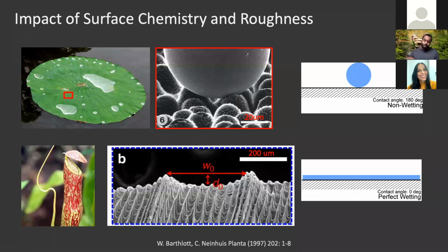And again, the opposite is true if you make a super hydrophilic surface, a surface that really, really likes water, like in the pitcher plant case. If you have this nanostructure and microstructure that really likes water, you're able to get almost perfect wetting, and you get something that's just a conformal coating of this liquid onto the surface. So this explains some of these natural phenomena that we may experience.